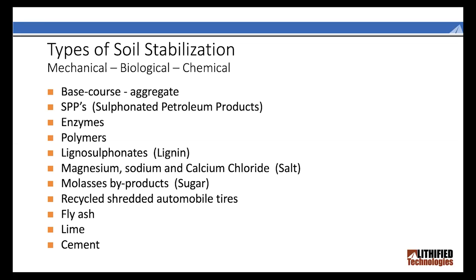So with cement, the ideal is when there is 6% or less clay content, it will be used in sandy soils. They will use it sometimes up to 10% clay content, but the higher the clay content, the less effective that it is. And so it's a window of just the sandy soils. Conversely, lime is used primarily when you're 20% clay or higher. 20 to 50 PI, plasticity index, is typically where lime is used. Once you get over a 50 PI, it's generally export time. They don't even try to stabilize it.